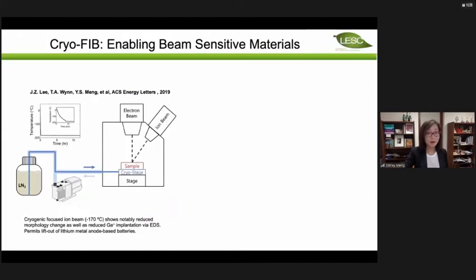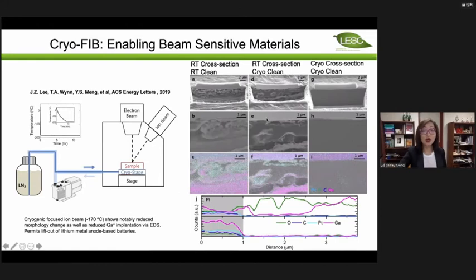So I'll show you an example. Literally, lithium reacts with everything. When I say everything, it means nitrogen, oxygen, carbon dioxide, water. Lithium reacts with everything. So when we do scientific instrument work, even if you use the focused ion beam to try to cut a fresh surface of lithium, the gallium ions actually alloy with lithium at room temperature. So if you do a room temperature cut of the lithium surface, everything you see here is artifacts. It's not the lithium surface that you're seeing.